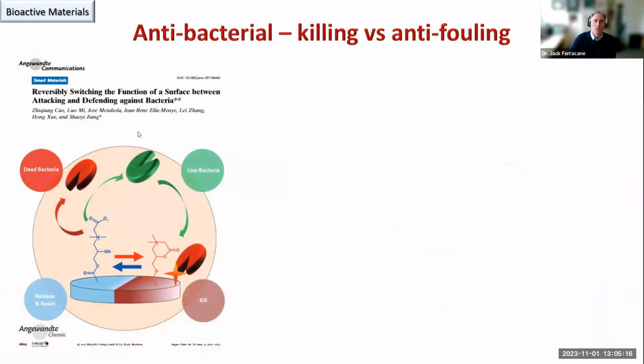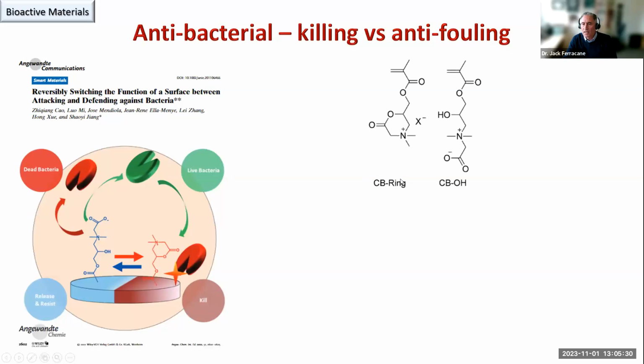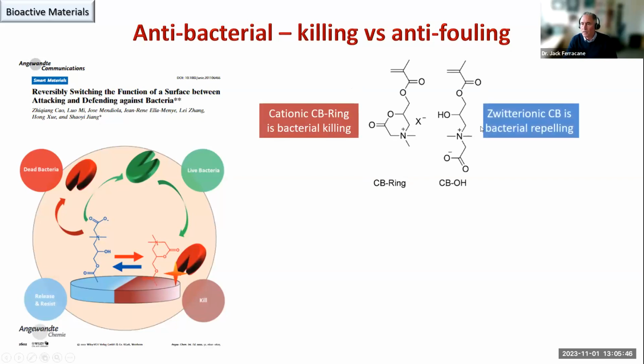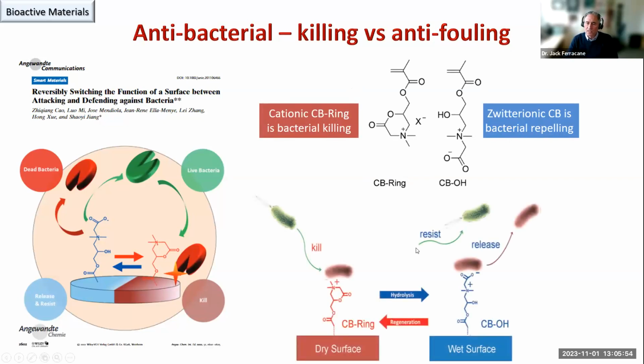Another area that's getting a lot of focus is the concept of Zwitterions, where you can have a molecule which can either kill bacteria or be an anti-fouling surface. So for example, we have this carboxybetaine ring, and in this case, in the ring mode, it's bacterial killing. Again, bacteria is killed by the positive charge on the nitrogen. Whereas if it's in an elongated state, a non-ring mode, it's bacterial repelling. So with this Zwitterion, this transition takes place, especially when it's in a solution.